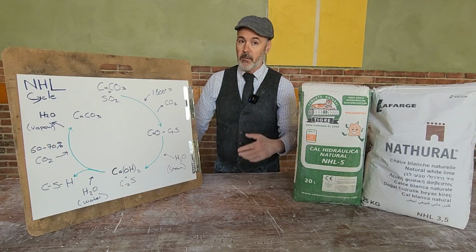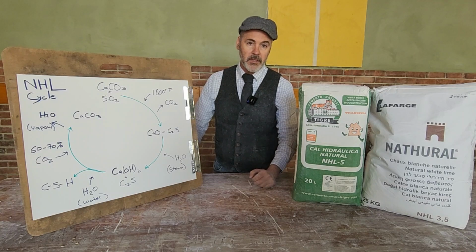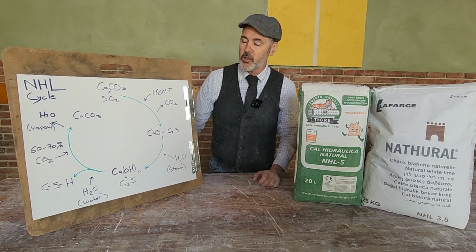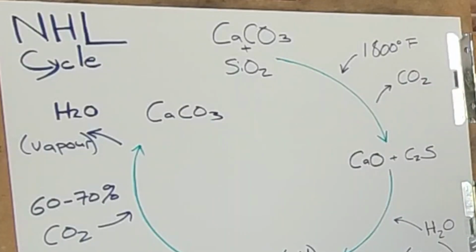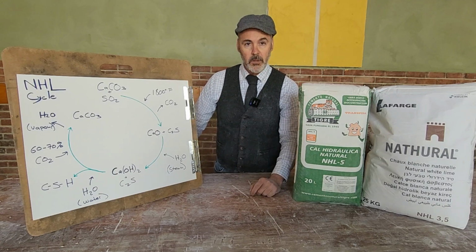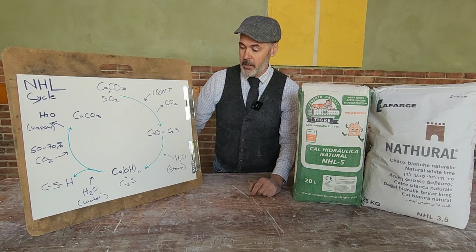Silicon dioxide may come from clays or other things that come from volcanic activity that have found their way into the porous structure of the limestone, lodged there. And to unlock its potential, what we do is add heat. That calcines the limestone. That heat is around 1800 or more degrees Fahrenheit. And typical of limestones, what you do is you calcinate all the CO2 out.